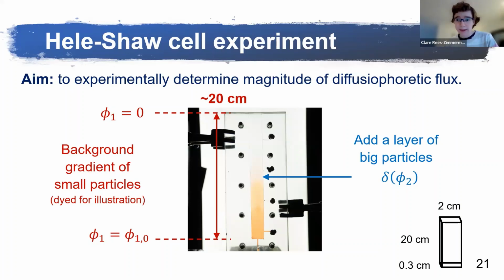Into this background gradient, I'm going to add a thin layer of big particles. And I want to determine the magnitude of the diffusiophoretic flux of these larger particles. If the large particles were not affected by the background gradient of the small particles, then they would be expected to diffuse symmetrically, but any asymmetry can be measured and will be evidence of diffusiophoresis.